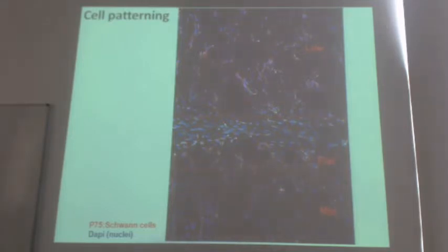So this ability to have different types of roughnesses on the top of solid surfaces can allow us self-patterning as well. Here you can see on the same scaffold different areas with low and mid roughness, and here is a flat silicon area between the low and mid roughness. As we can see, in the low roughness there is a spontaneous orientation, and when one goes to the mid roughness, there is a specific orientation of the Schwann cells on the top of the structure.